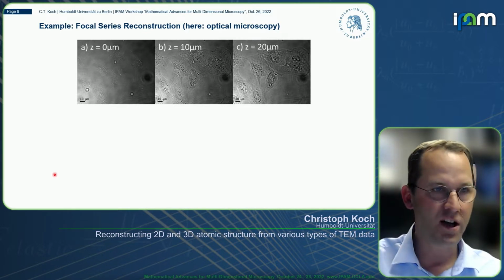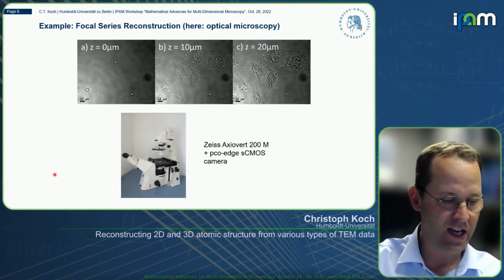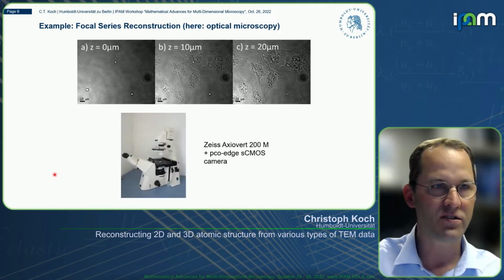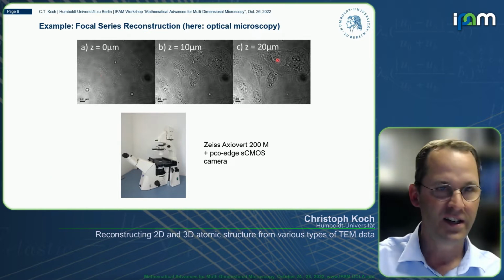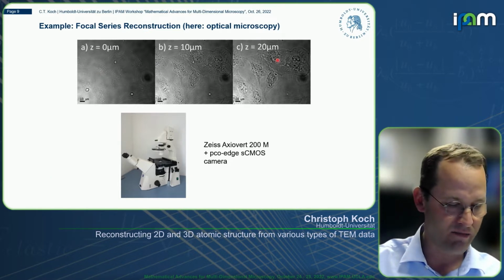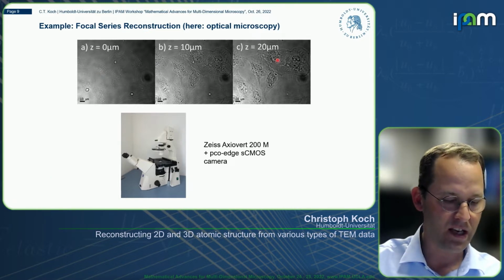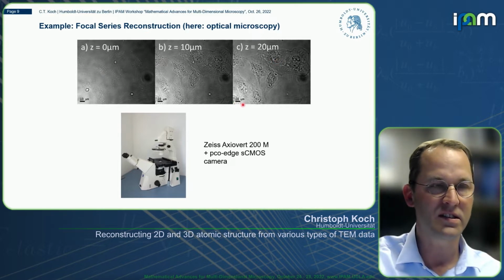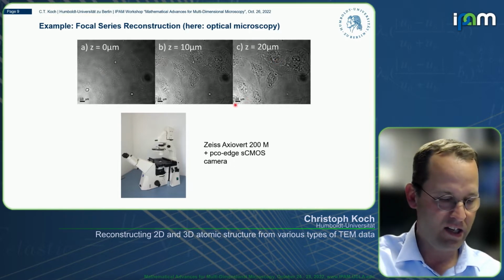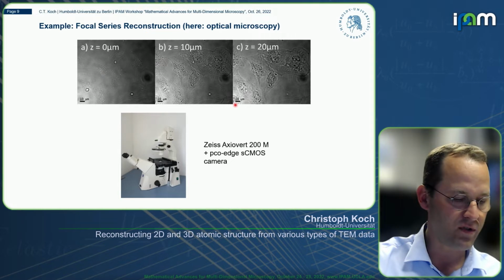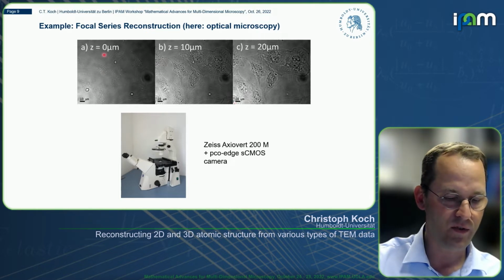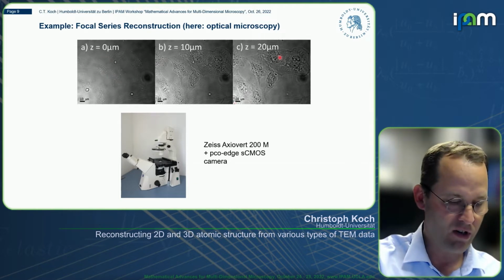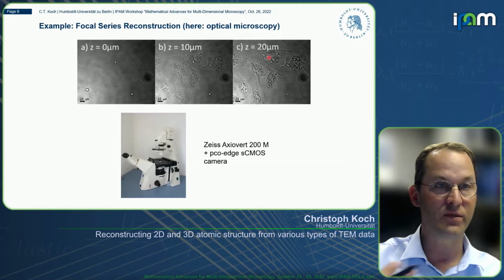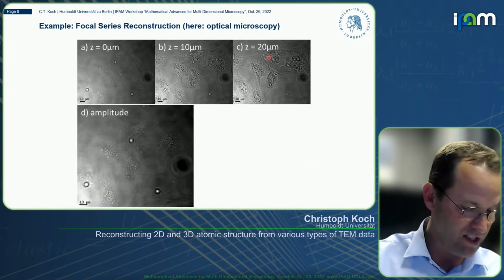So this is a simple optical microscope, and what you see up here is not the atomic structure of something very strange, but it's on a much larger scale. Namely, if you look at the scale bar here, this is a 10 micron scale bar. These are just cells, live cells in a liquid. And if you record a focused image, you don't see anything. If you defocus more, you actually see much more contrast. And then if you apply some reconstruction algorithm, you see much more.